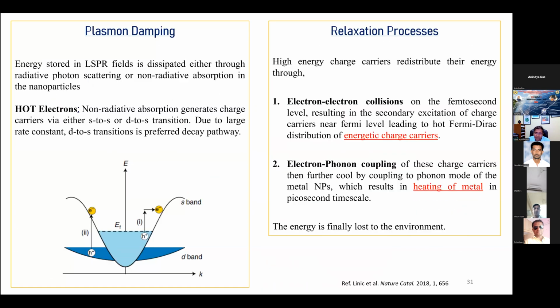Now, the only problem with these processes is that a typical gold or silver nanoparticle, say 5 to 10 nanometers, absorbs only some portion of the visible light, some portion of the sunlight, around 530 to 550 nanometers. But if I really want to develop a photocatalytic system, I need to absorb the entire solar spectrum, from visible to near IR.